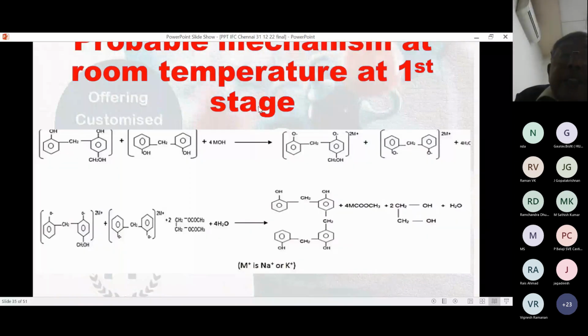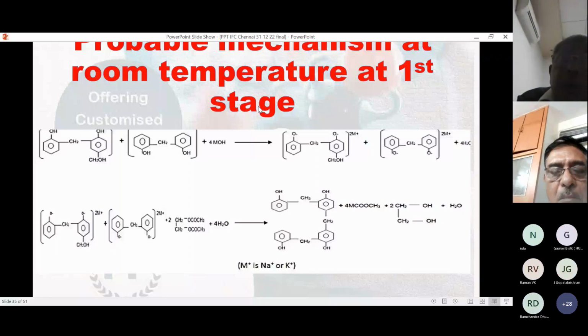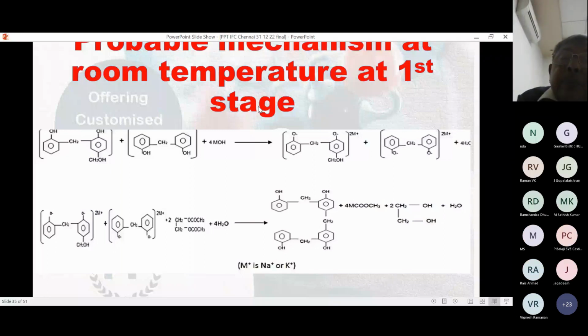This is a mechanism I have tried to establish for the first stage of curing. See, curing always means formation of lateral primary bonds and conversion into a thermosetting material. So the first line you can see is a linear chain. Second, some lateral chains have formed. So this gives the molds and cores made out of your Alphaset bonded sand strength which is sufficient from stripping right up to closing. So basically it is a dry strength.